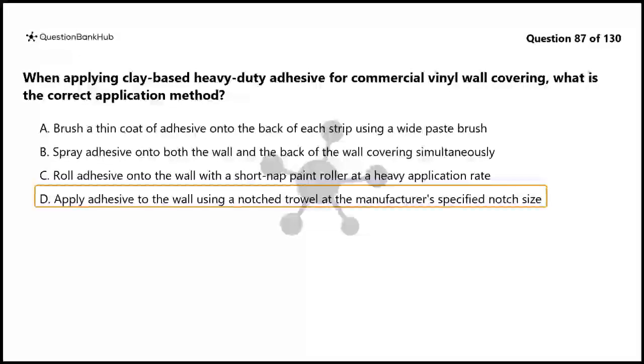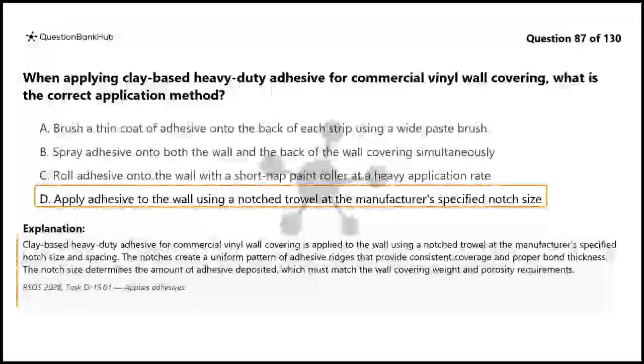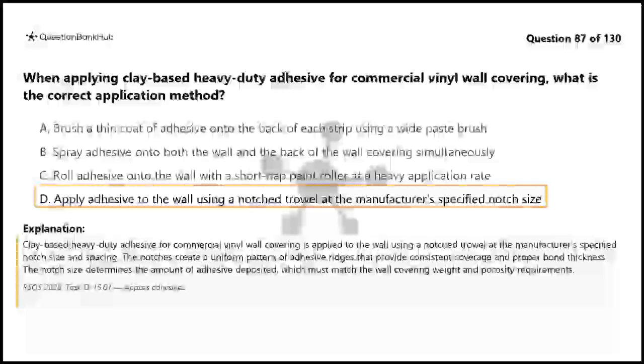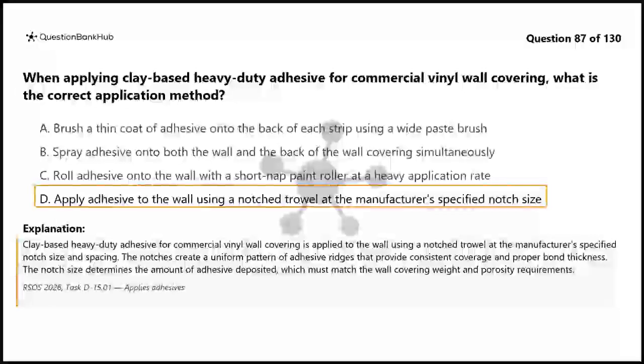The correct answer is D. Clay-based heavy-duty adhesive for commercial vinyl wall covering is applied to the wall using a notch trowel at the manufacturer's specified notch size and spacing. The notches create a uniform pattern of adhesive ridges that provide consistent coverage and proper bond thickness. The notch size determines the amount of adhesive deposited, which must match the wall covering weight and porosity requirements.